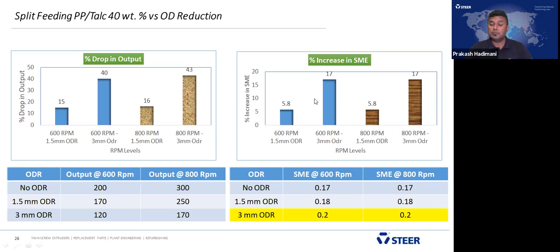If you calculate the increase in SME: 5.8% at 600 RPM for a 1.5 millimeter OD reduction, 17% at 600 RPM for a 3 millimeter OD reduction. 5.8% increase in SME at 800 RPM for a 1.5 millimeter OD reduction, 0.75 millimeter per side. And 17% increase in SME at 800 RPM with 1.5 millimeter per side OD reduction.